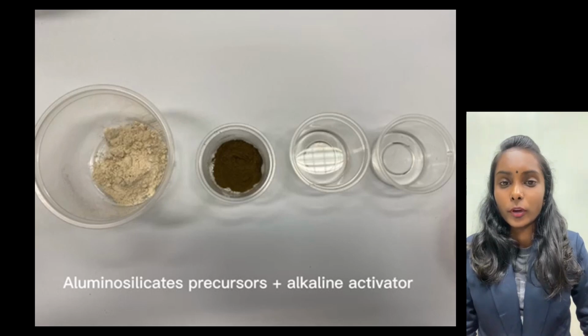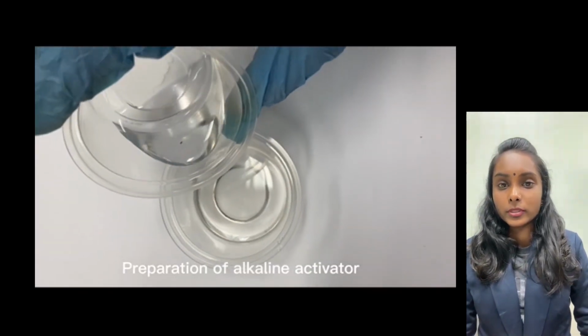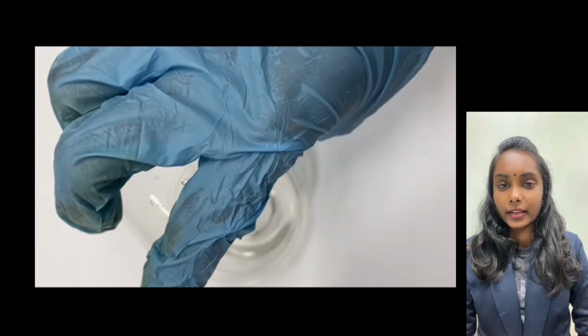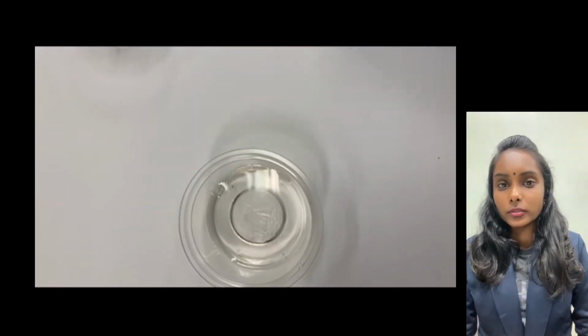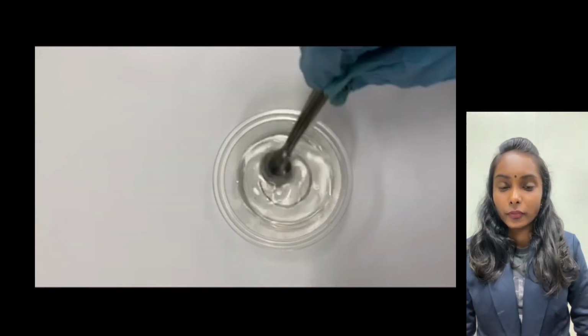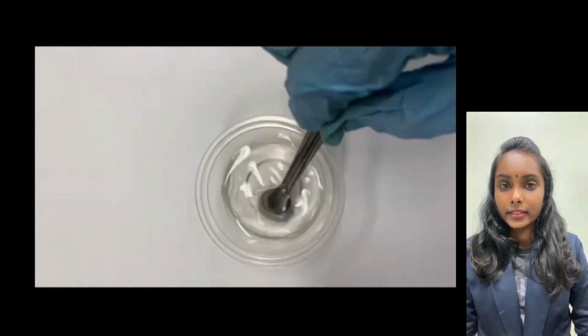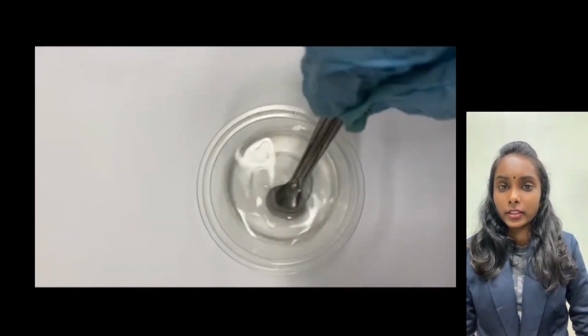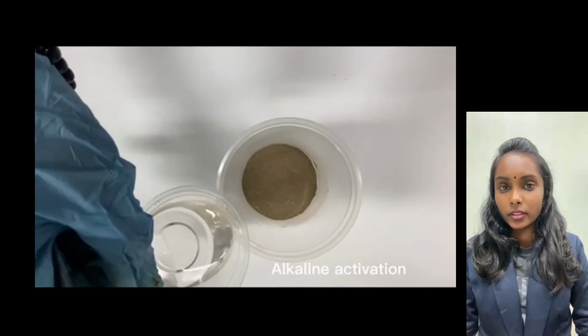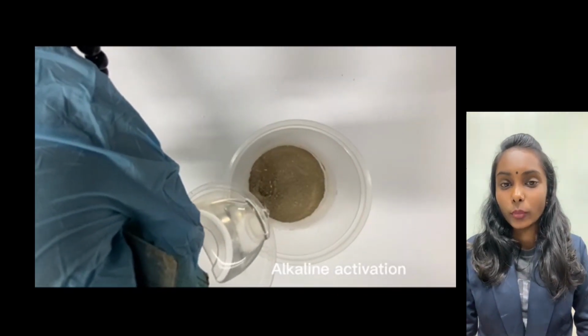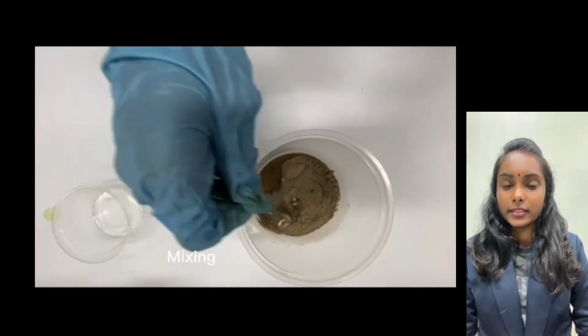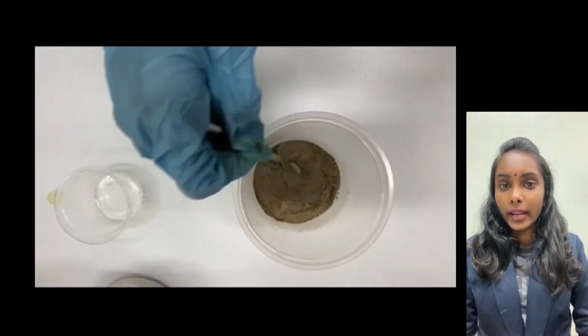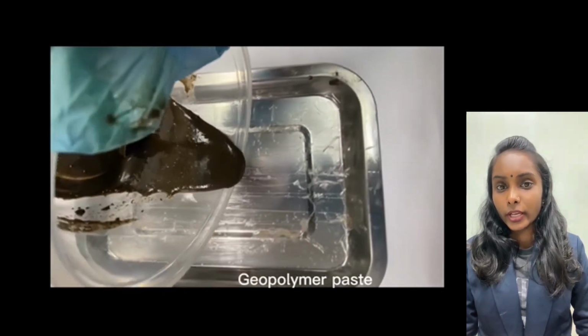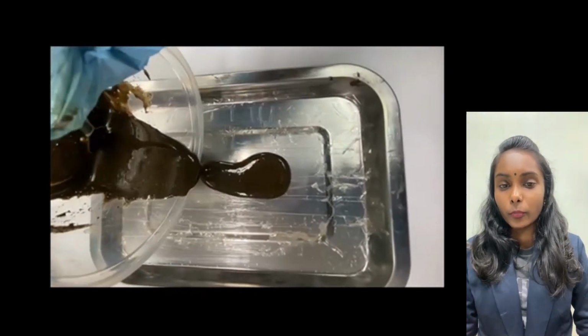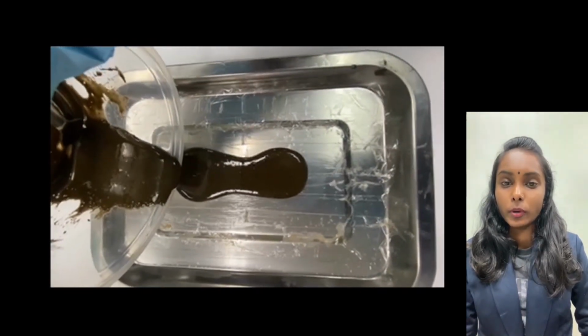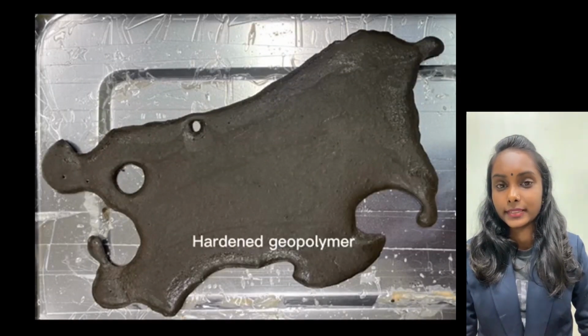Now let's look at geopolymer sample preparation. The geopolymer process starts with aluminosilicate precursor and alkaline activator. First of all, the alkali activator is mixed well for 15 minutes, and then the prepared alkali activator is poured into the aluminosilicate precursor and mixed well to obtain geopolymer paste. After that, the geopolymer paste is placed in an aluminium plate and then put in an oven to obtain hardened geopolymer, and then crushed into powder particles for the adsorption process.